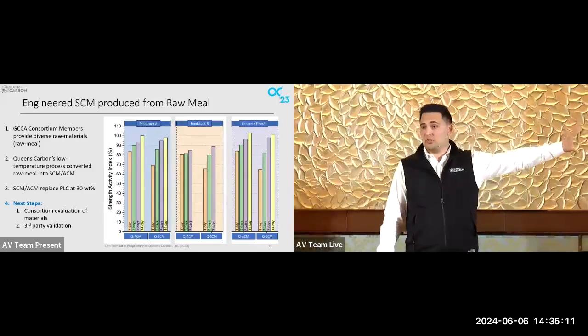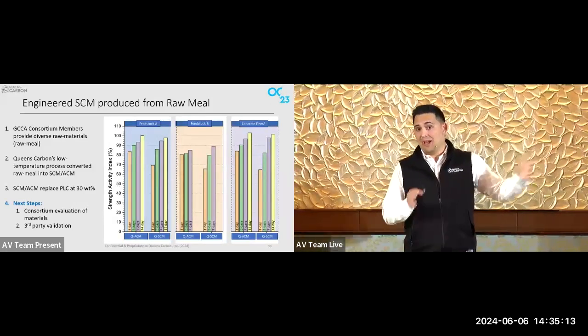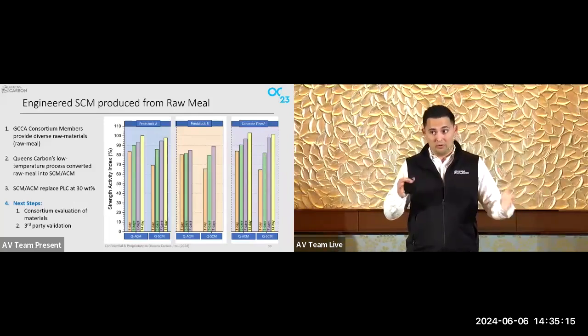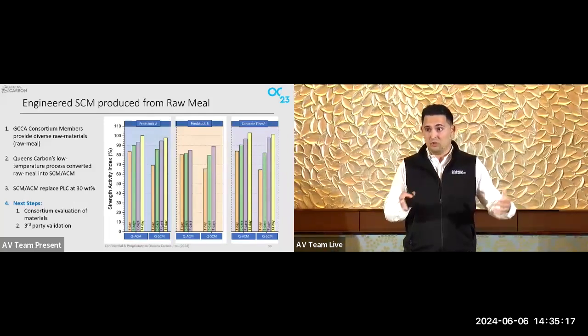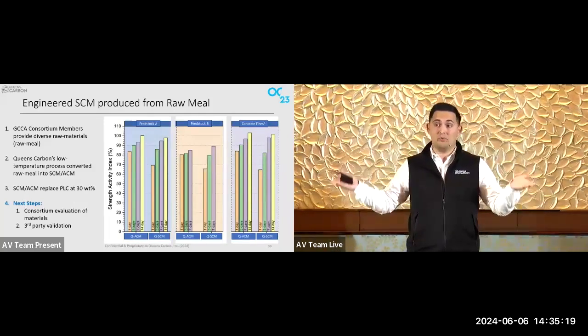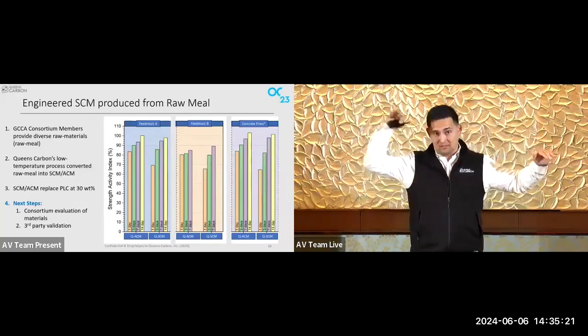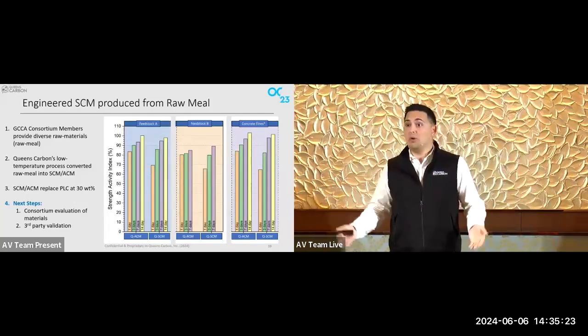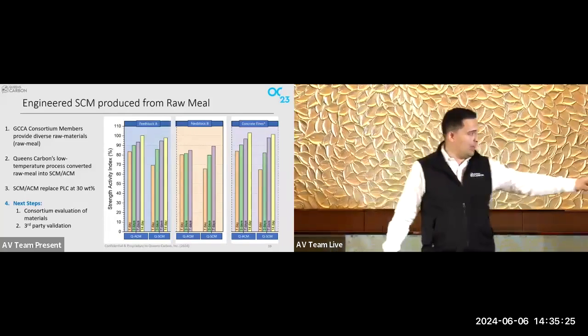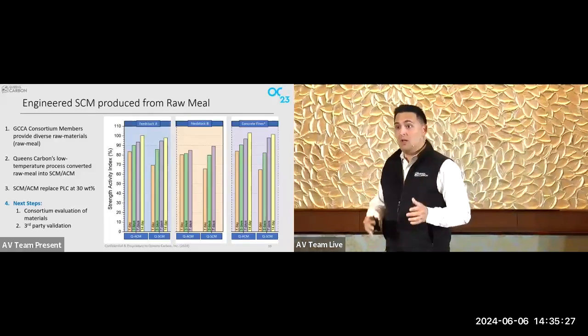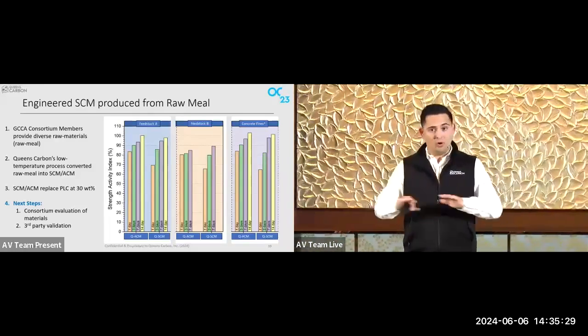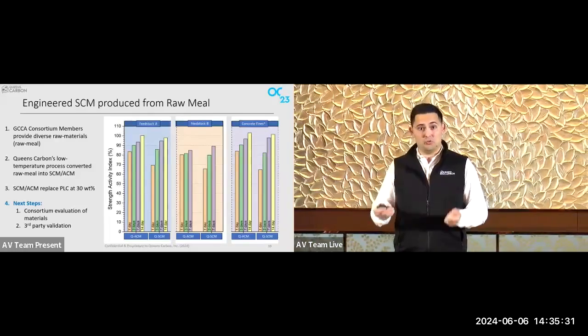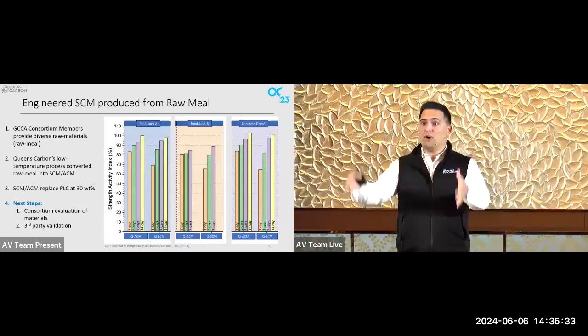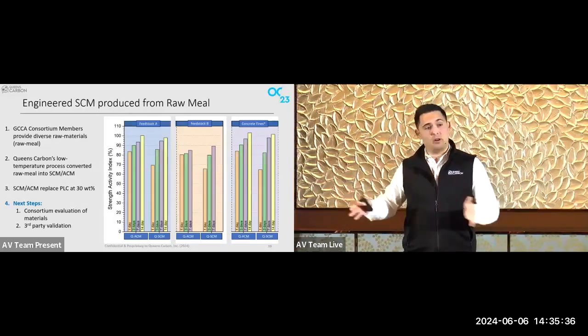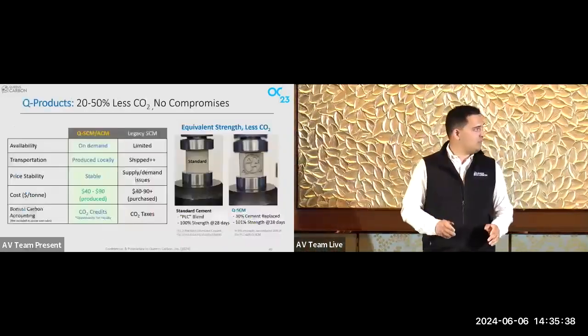This is a 30% PLC replacement. So if you add the limestone that was already in PLC, we're already reaching about 40% in terms of clinker replacement. In the lab, we've done up to 40% replacement without including the PLC. We believe we can go much higher. I mentioned the ACM product is a hydraulic product. Our hope is longer term, 100% replacement. When the industry is ready to retire the kiln, put our Q reactor in place. Until then, put it in parallel and don't disrupt your process.